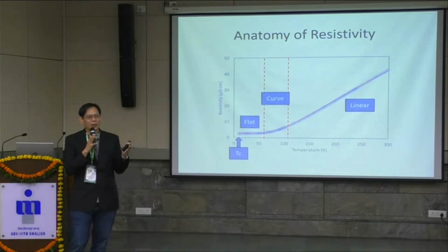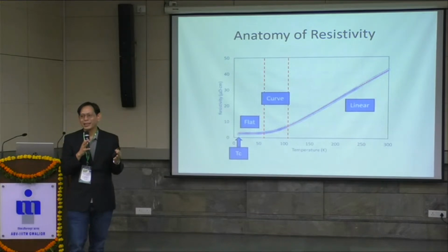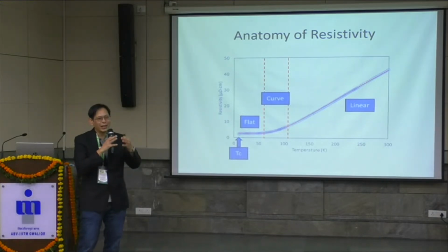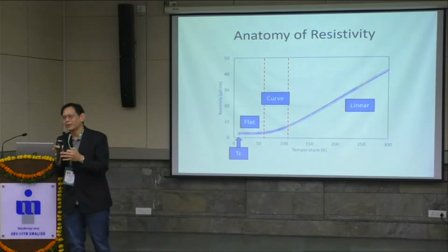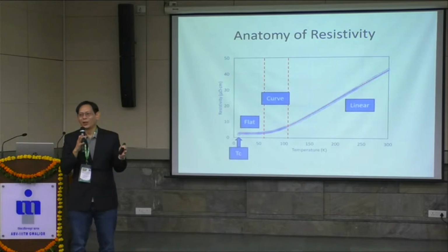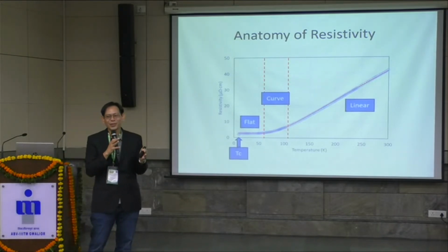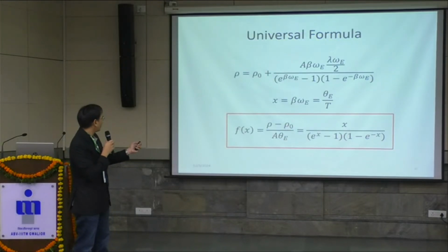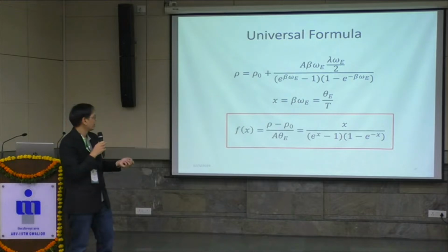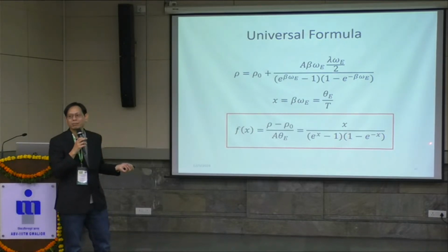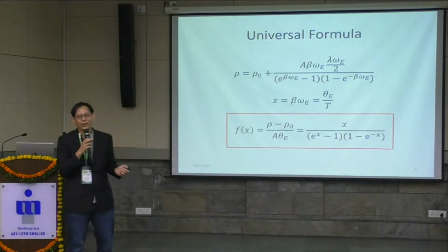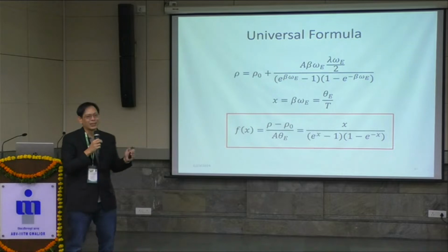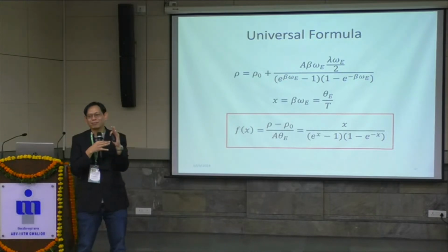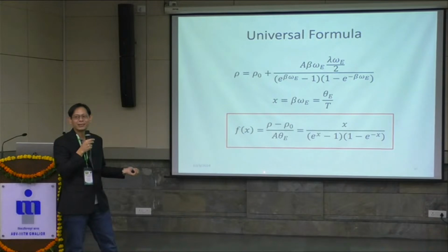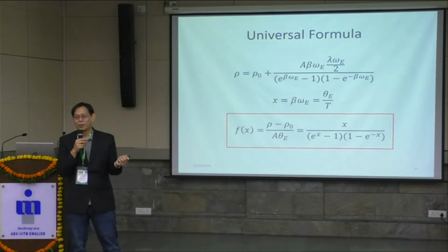There is some kind of universality in this resistivity formula, because even with different compounds, different metals, different compositions, all the resistivities look the same. So there must be something universal about it. So we did some transformation on our formula, and we find that we have a function that depends on x only. You put x into this equation, you get some number, and you put in another x, you get another number. So you can establish a graph that depends on x only, not on any system or compound. I call this the universal formula.